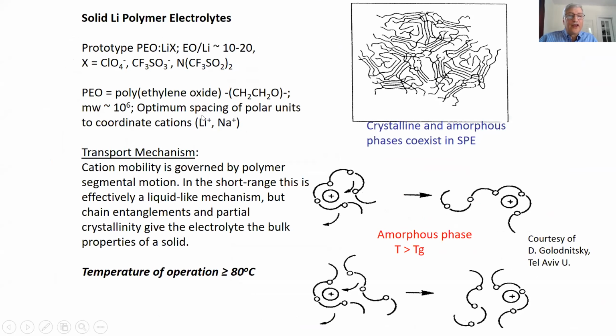So let me just move to the, most of the polymer electrolyte research is on polyethylene oxide, PEO, right? It's a very interesting material. It's been studied for almost 50 years. Basically you have this amorphous and crystalline mix of materials. The ions can only move in the amorphous phase and only above this temperature called the glass transition temperature, and only above the temperature where the crystalline phase is melted. The net effect is that these are great electrolytes, but only above 80 degrees C. So that obviously eliminates a lot of applications.